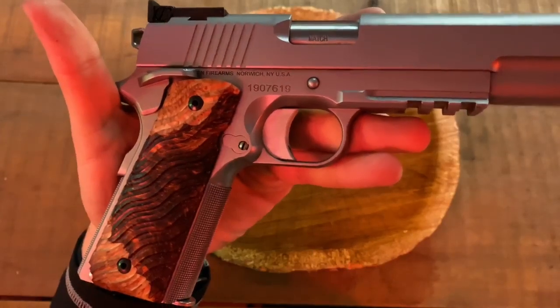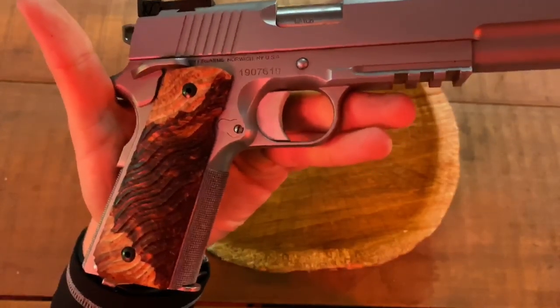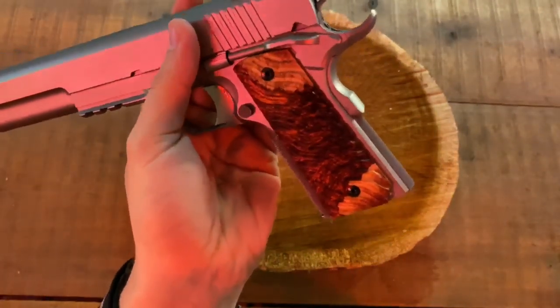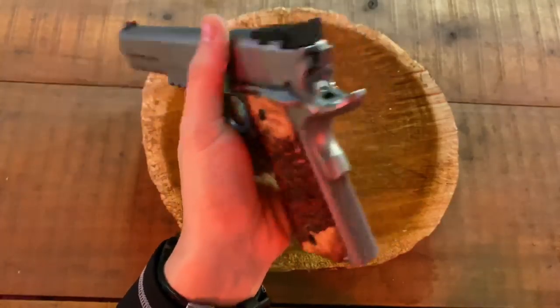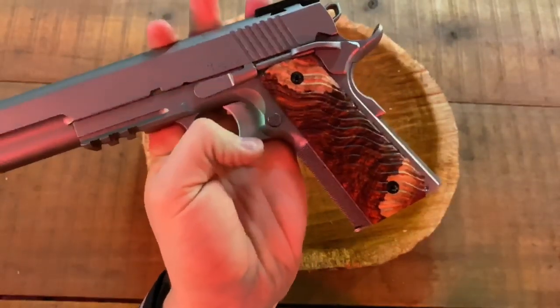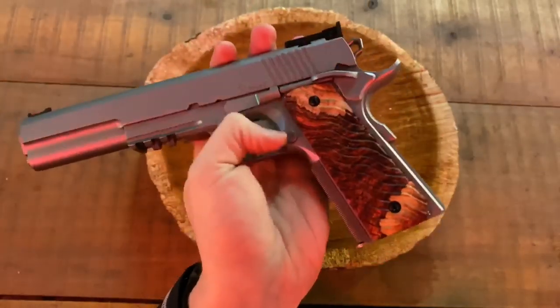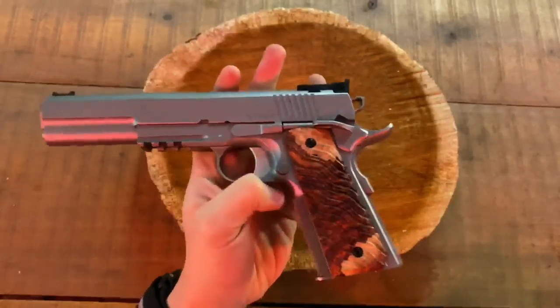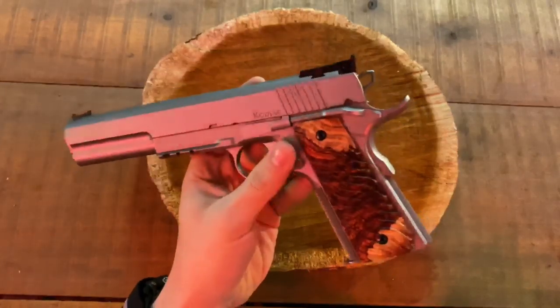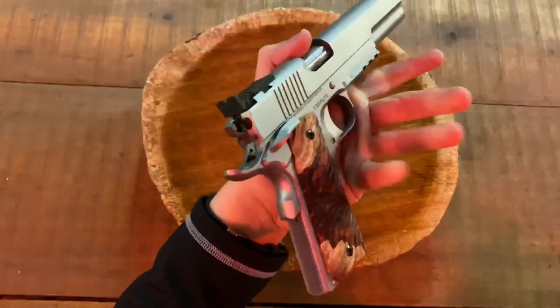Burl wood has a swirly, beautiful grain structure with pointed curving edges, and maple burl is more sought after and expensive than a regular piece of maple wood. Stabilization is a process in which you soak the wood in a pool of resin and pull a near-total vacuum on it — all the air bubbles out of the grain. Then you release the vacuum, the wood sucks in the resin, and is submerged. You then bake the wood in an oven to set the resin, making it extremely hard and tough — similar to G10 toughness. From there, pieces of live-edge burl are placed in blocks, dyed with pigmented epoxy resin, and placed in a pressurized pot to squeeze out any bubbles while the resin cures.